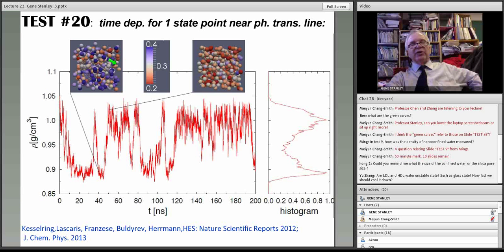And the little pictures up here are snapshots. This snapshot is in the low density phase, and the blue corresponds to well ordered. This color scheme is a measure of the local order in the liquid. So where you see blue, it means well ordered, as in LDL. And where you see red, you see less well ordered, as in the HDL. So as a function of time, we expect the system to flip from well-ordered to less well-ordered, and then back again, because that's what you see here. Well-ordered to less well-ordered, and back again, at all different time scales.